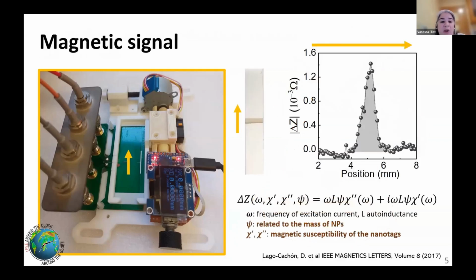This is a typical measurement of a scan of the test line of the lateral flow assay. We can see that when the nanoparticles approach the sensing coil, their switching magnetic moments will produce some eddy currents at the surface of the coil, which will increase the impedance of the circuit. So we can see here a peak of the impedance. What we take as the magnetic signal of the test line is the area above this peak, to account for all the nanoparticles in the test line.